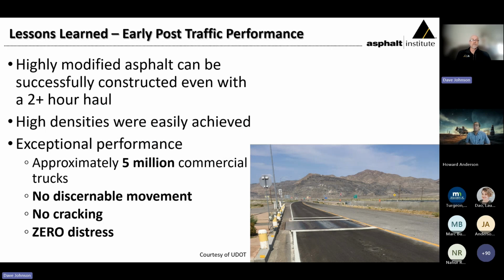So how has it gone? Well, what we learned is that highly modified asphalt can be successfully constructed even with a 2-hour haul. And this has been something that has come into play with projects since 2021 when this was built, where they do have some longer hauls with some of this material. High densities, as we saw, were easily achieved. So far, this particular location has seen over 5 million commercial trucks, and quite frankly, there's nothing wrong with it. There's no discernible movement, absolutely no cracking, and zero distresses that could be of note.